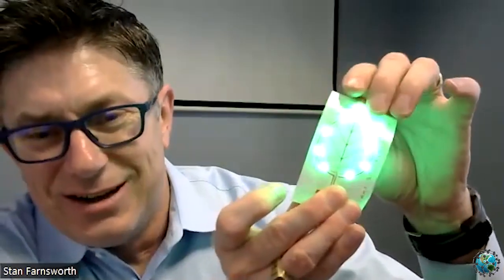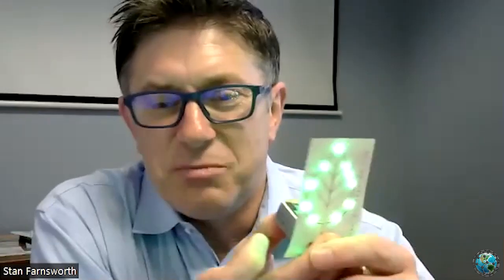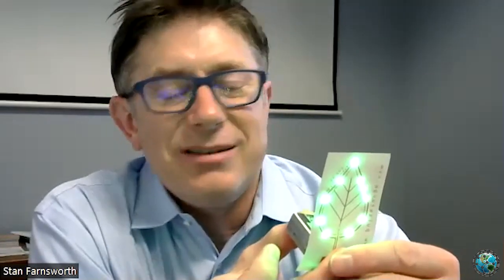that have been soldered onto the outline of this piece of plastic, of this leaf on this piece of plastic. And in many ways, this seems fairly simple, and maybe the complexity is so ingrained in it that we don't even think about it. But really, it should be impossible to make this in many ways. It should be impossible in one sense, because the soldering process itself requires very high temperatures to melt metal. Solder is metal, and we're melting metal at 200 degrees C up to 250 degrees C. So it's not a low temperature solder, but we're doing this on plastic.